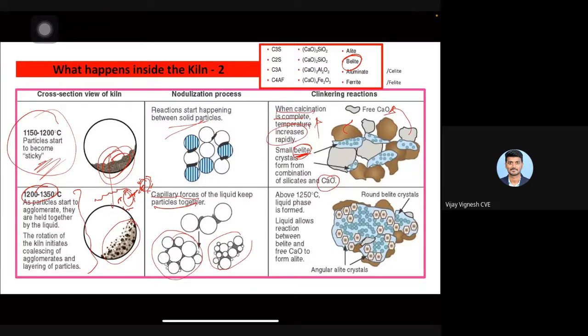Above 1250 degrees centigrade, the liquid phase is formed. This liquid allows the reaction between the belite, which is nothing but dicalcium silicate, and the free calcium oxide to form alite. So belite and calcium oxide create alite. So you can look at the microscope. You can see here rounded belite crystals form. So angular alite crystals form.